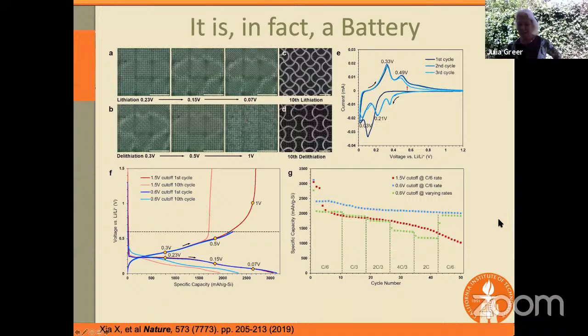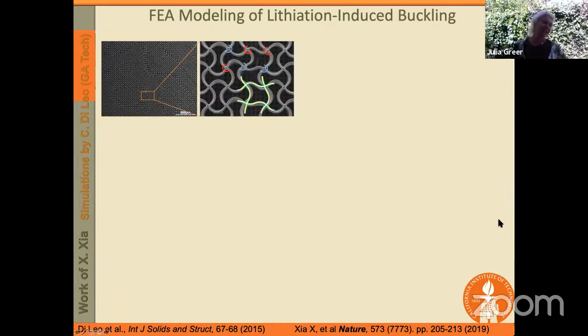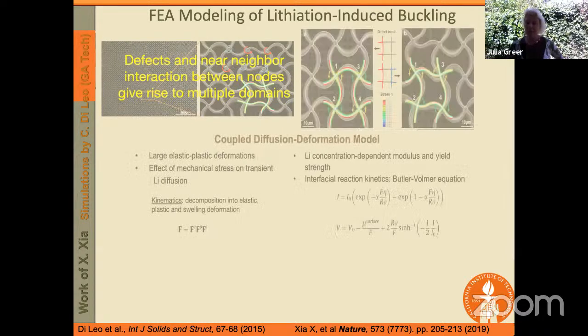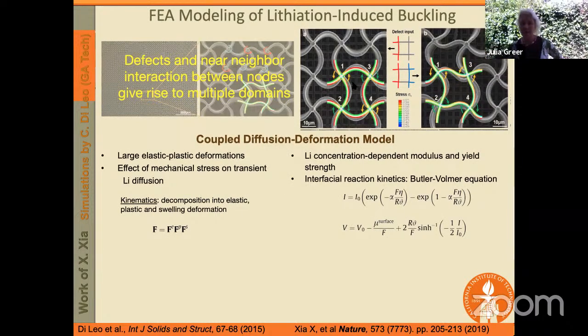But here's what's interesting about this battery: we discovered in the process of charging and discharging it at different rates that sometimes the nodes all co-rotate. And this is when you have this very nice architecture. And sometimes some of them co-rotate and some counter-rotate. So when they co-rotate, you create this very nice buckling pattern. But when they counter-rotate, you create the second mode buckling. And this leads to a very frustrated architecture.